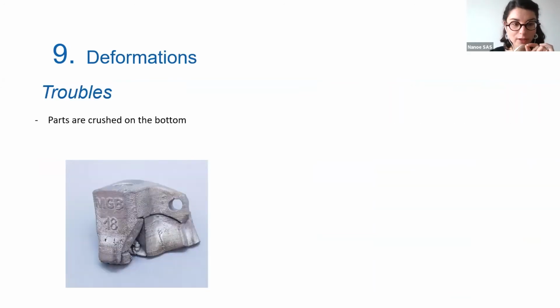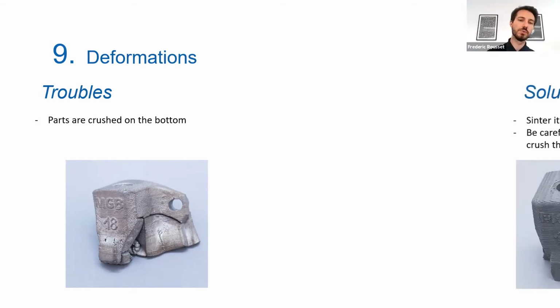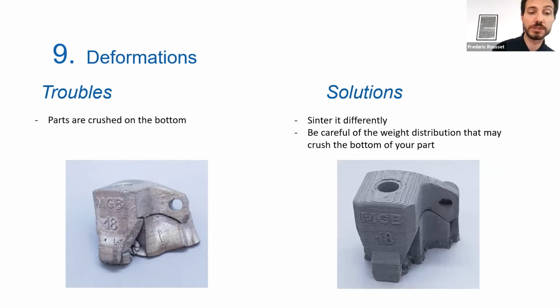Another kind of deformation is when the deformation is only on the bottom, like in the picture. So what does it mean, what is happening, and how to avoid this? For this problem, we recently discovered it because it is quite rare. But if your parts are quite crushed on the bottom, as we can see on the photo, you can try to sinter it differently. This means that you can try to turn your parts upside down and see if it helps, because you redistribute the weight of your parts inside it.